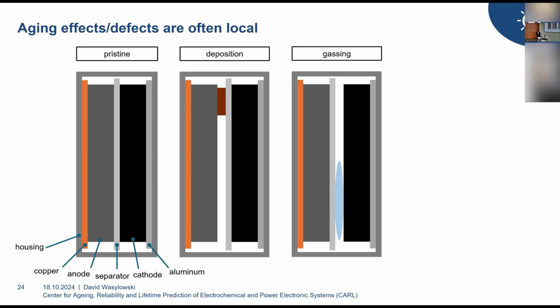And another typical local aging effect is gassing. So again, if you have some unwanted electrochemical effect between the electrolyte and the electrodes, which is somehow locally motivated, there can be gas produced, and you can also imagine that you do not want this gas in your battery cell because this gas accumulation is blocking lithium ions from traveling between the cathode and the anode.